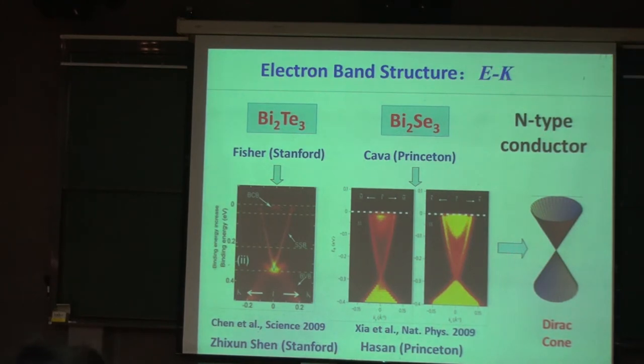If you look at group six, you have oxygen, sulfur, selenium, and tellurium. If you evaporate by heating the raw materials, the volatile form of these materials is always in the form of molecules. So you have to break the molecule to react with the bismuth, which is in the form of atoms. In this case, the molecule is strongly bonded together, so it's difficult to separate them. And that's why you always have vacancies of tellurium and selenium. That makes the materials n-type conductors.